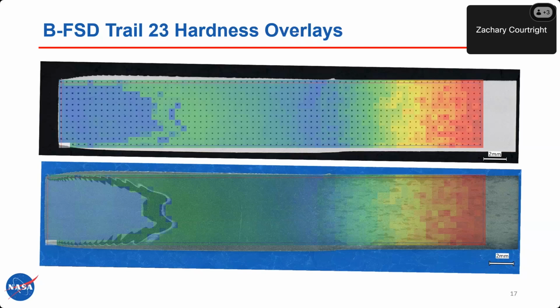But there's also kind of a revolution of new alloys that are being released specifically for additive processes that do not require quite the level of post processing to get to the properties. But in general, I mean, rather than having to take a large sheet, cut an isogrid structure into it, bump form it into a shape, and then weld that together into a cylinder, and then weld a dome onto it, or have a ring forging that takes 2 years of backlog to make and has 95% of it get machined away to get to the final product.